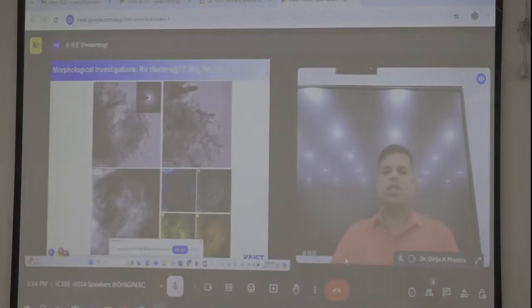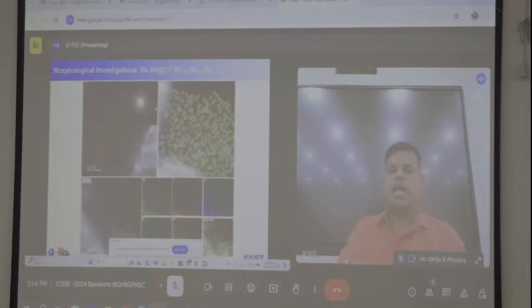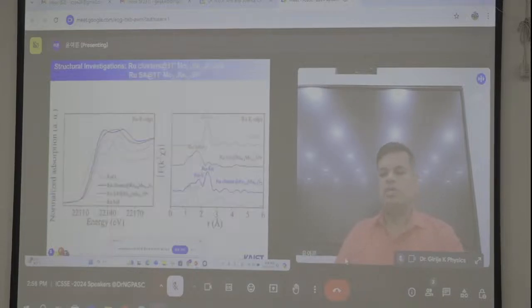So when I make the material, first I make the cluster particles, because usually when my plan is going to make the high loading, I get the cluster particles. So the interesting thing is I do some transformation via a new technology. Maybe I have not reported this material yet because we are aiming for some other big journals. So I transformed it from the cluster to single atom. You can see there is a high transformation from the cluster to single atom.